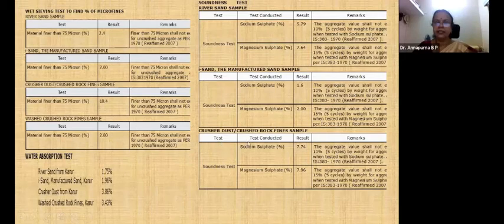And the crusher dust, or the crushed rock dust fines, has 7.74 and 7.96 because the dust contains more silt and it is not taken care of. So the manufactured sand has the least effect due to sodium sulfate and magnesium sulfate. So it is within the 10%. All these fines are within 10% aggregate value, but the better quality is the manufactured sand, which has the least.